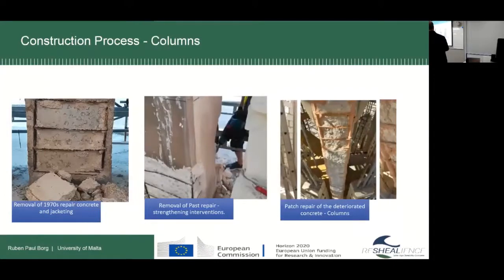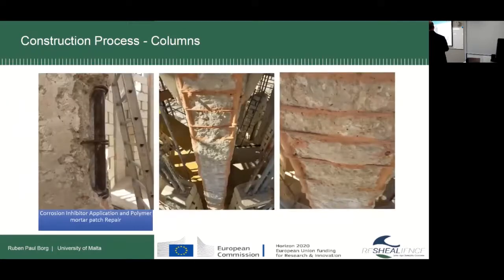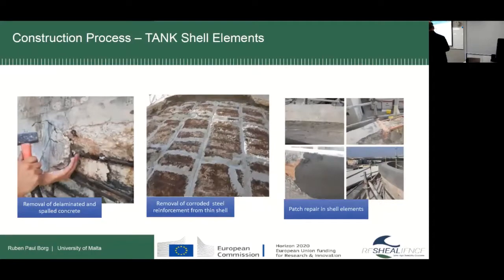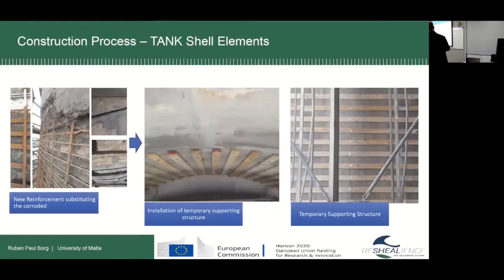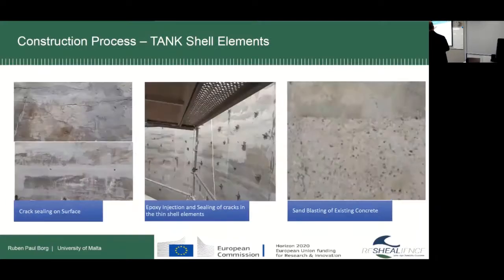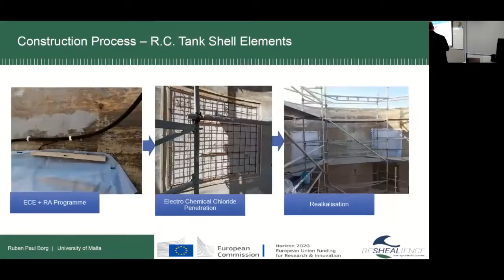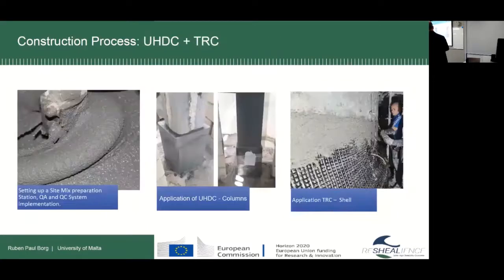These were some images, removal of the cover. The tower was already retrofitted in the 70s, so there was already a 7 centimeters jacketing above, which had to be removed. It was the removal of the past intervention and the treatment of the existing material. You see application of corrosion inhibitor and mortar repair, and this was done, patch repair of elements which were needed, different images of the site, and epoxy injection and sealing of cracks, different operations.